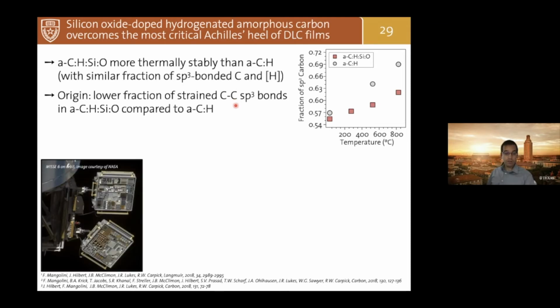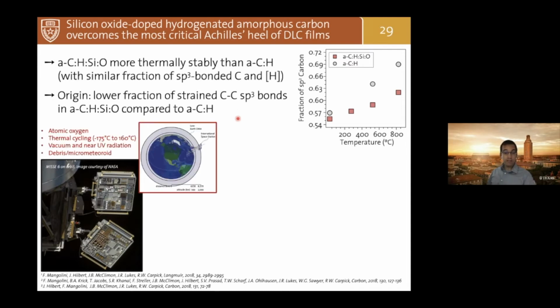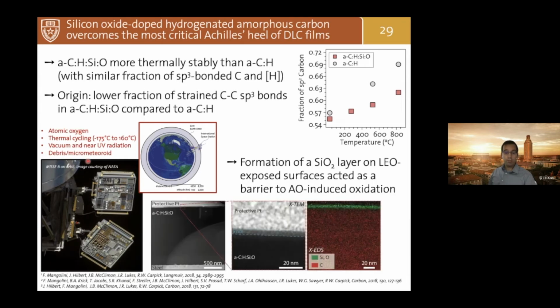We were also very fortunate to participate in the Materials on International Space Station experiment between 2011 and 2012. Basically, this material was sent aboard the International Space Station for a year and a half, where the material was exposed to thermal cycling, vacuum, and ultraviolet radiation, as well as, most importantly, atomic oxygen. Atomic oxygen is a great issue for materials on satellites because of its high energy as well as its high flux.